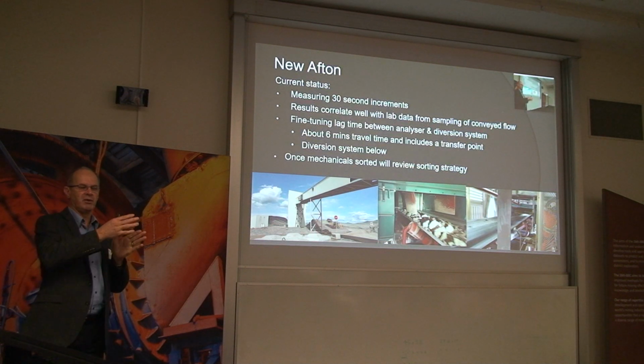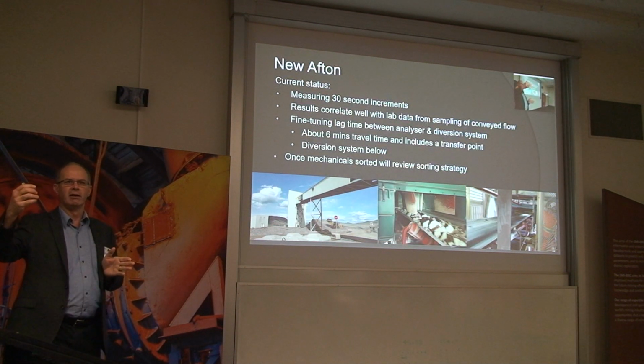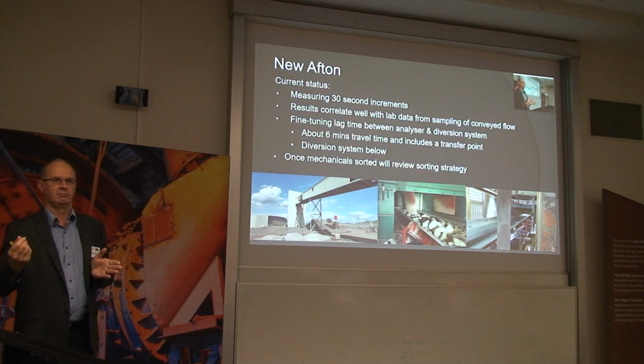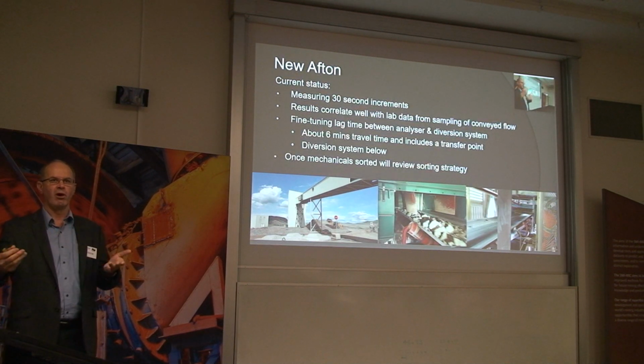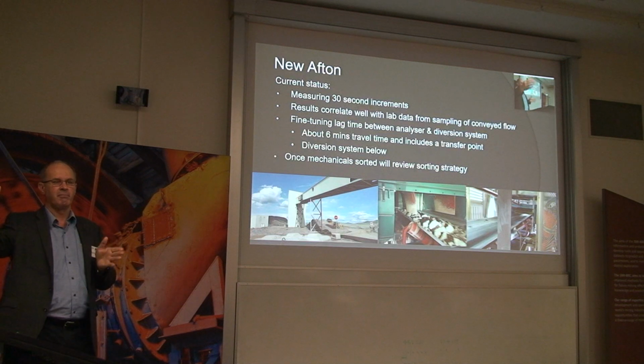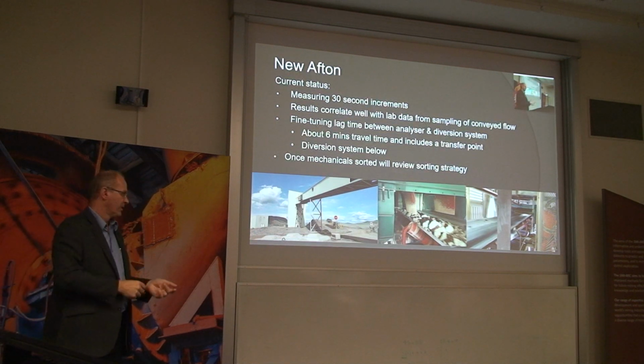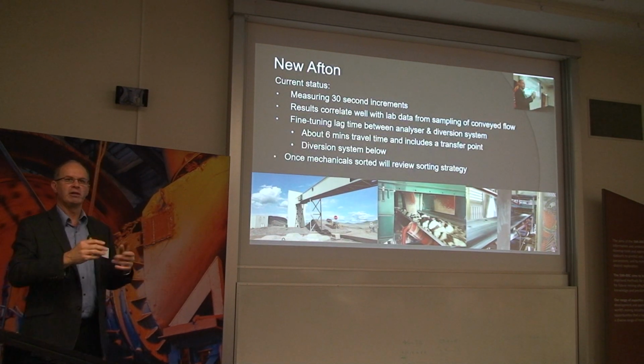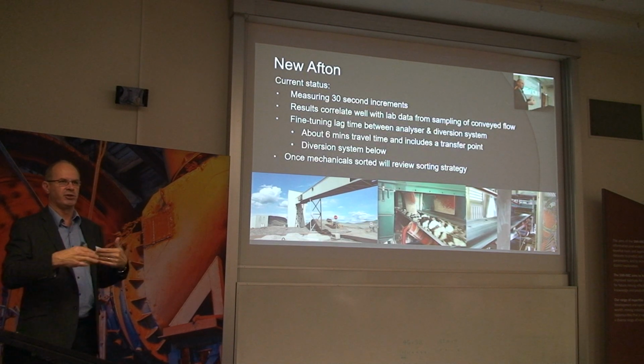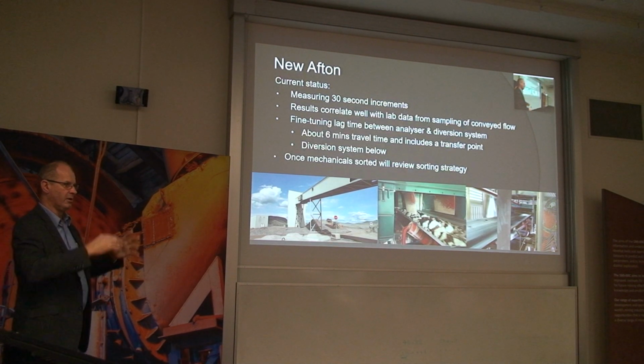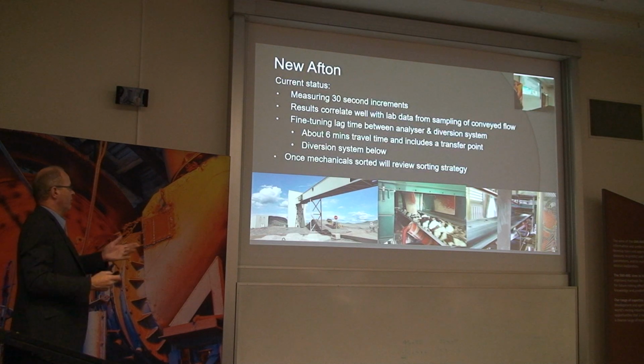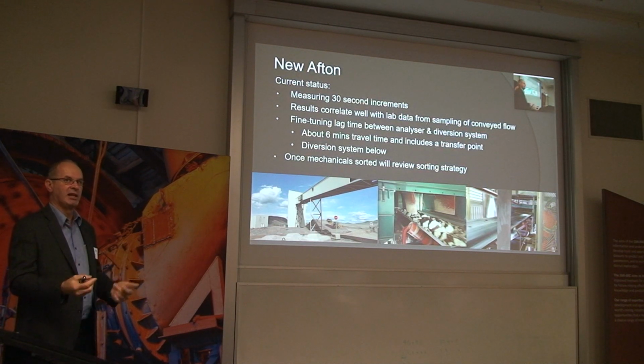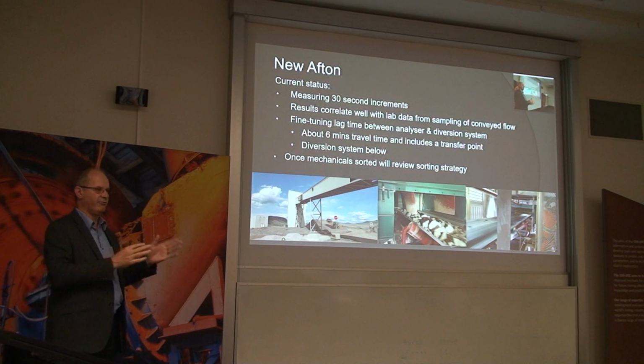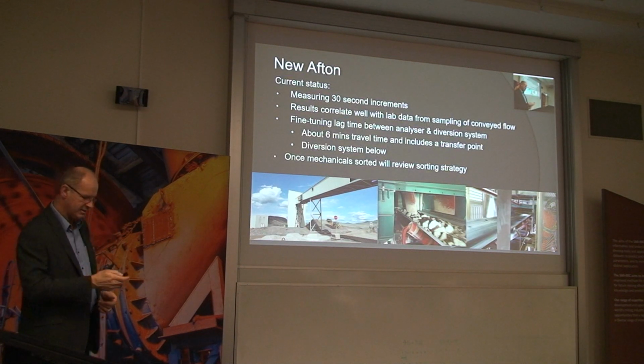Normally, we would put it at the start of the conveyor, at the end of which you're diverting, because then you have more confidence in your lag time. If you've got to go through chutes and other transfer points, you've got more delays, some of which you can't control. Depending on the flow of the material, you might get a couple of seconds of delay longer than you expect, and therefore your selected increment isn't as accurate as you hope.